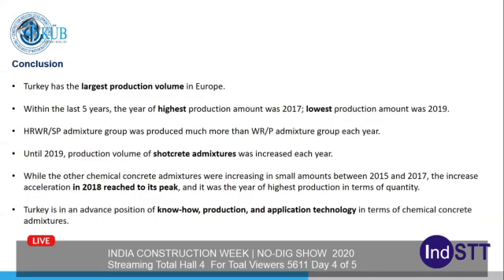And the high range water reducer super plasticizer admixture group was always produced much more than the water reducer admixture group in each year. So the gap actually started to decrease when we compare the last 2 years, but again, high range water reducers were always higher than the water reducer groups.